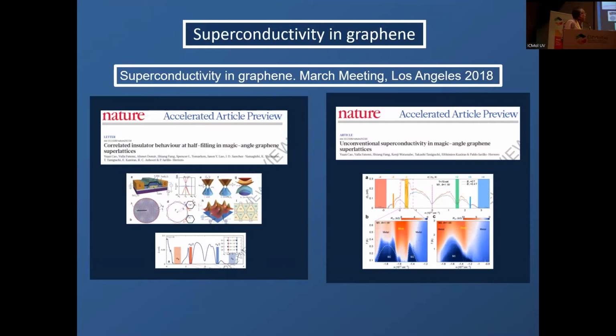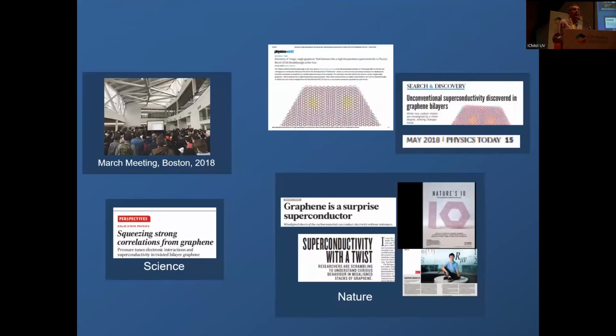And the thing was that the group of Pablo Jarillo-Herrero at MIT discovered that by twisting one graphene layer with respect to another, so the sample was just a graphene bilayer, but not a garden variety, regular graphene bilayer, but a bilayer where the two layers were twisted relative to each other by about 1 degree. The system shows superconductivity and insulating behavior in a very complex phase diagram. It immediately became a sensation. A lot of people have been working on that.